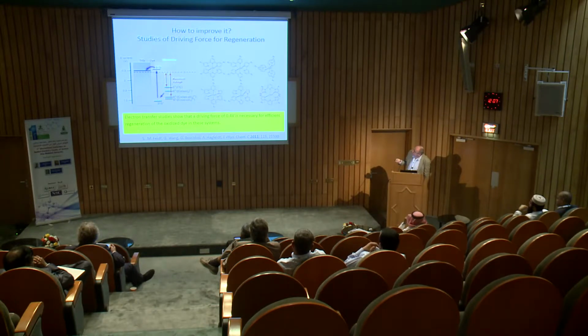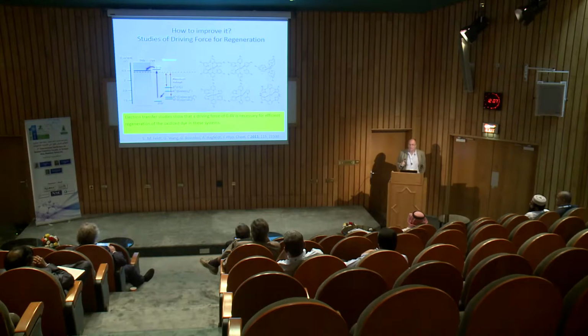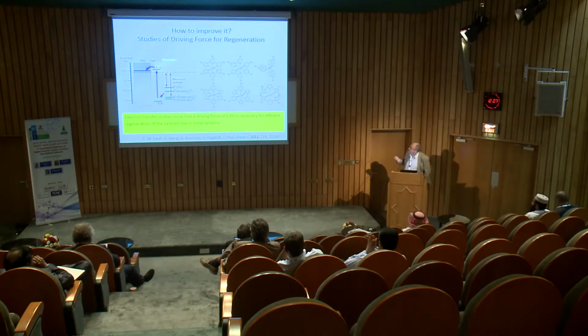And what you can do then is a classical electron transfer theory process. You can study how much the potential difference, delta G, free energy you have between the electrolyte and the dye, and then measure how fast the kinetics is, how fast this process goes, and then find the optimum, let's say, or the driving force you need for efficient regeneration. And to make a long story short, we are down to about 0.4 volt needed in the gap here to regenerate the dye efficiently. So we took it from iodide 0.7 volt with cobalt to 0.4, and the question is, can we do even better?